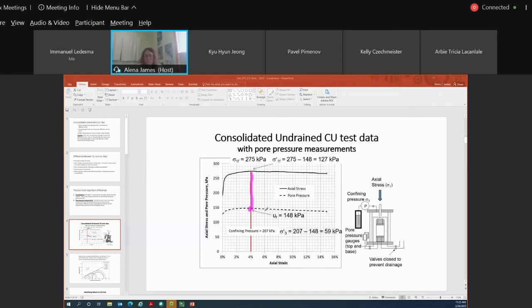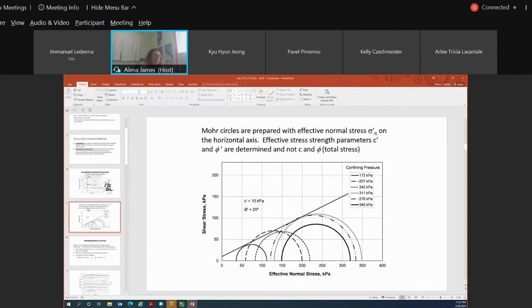And our effective confining pressure is similarly calculated. We know that our total confining pressure is 207 kPa, and we will subtract our pore water pressure to get our effective confining pressure. And this is important because if you look at these plots here, for a CU test, we're plotting our shear stress on the y-axis versus our effective normal stress. So the key difference between a CU test and a UU test is this word effective, because effective indicates that you've taken away or subtracted your pore water pressure from both your confining stress or confining pressure and also from your axial stress. So what you're plotting is slightly different, so your axes should be labeled differently as well.